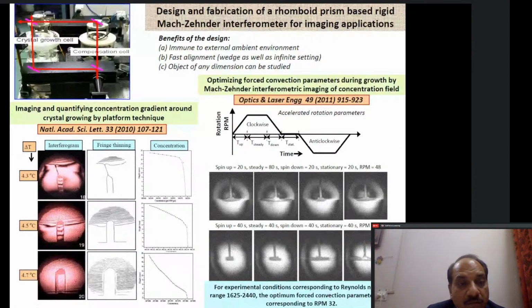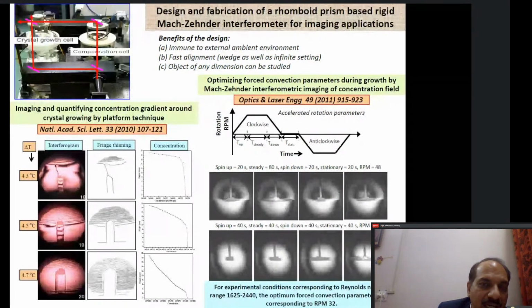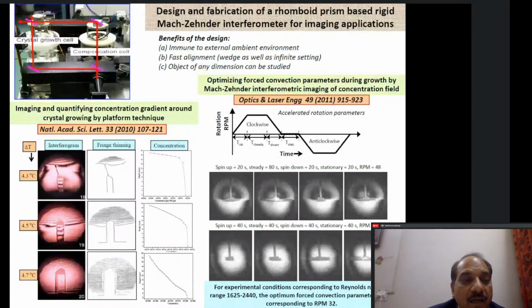And in fact, when there is an inclusion, we try to dissolve the crystal slightly. So we increase the temperature so that the solution near the growing crystal becomes undersaturated, and that region where the inclusion has picked up gets dissolved, and then we give a small cooling. So these types of online feedback mechanisms, these optical techniques, have provided us, and that is how we have been able to tailor-make our growth process and optimize our growth conditions so that we get good quality, large size crystals required for our programs.